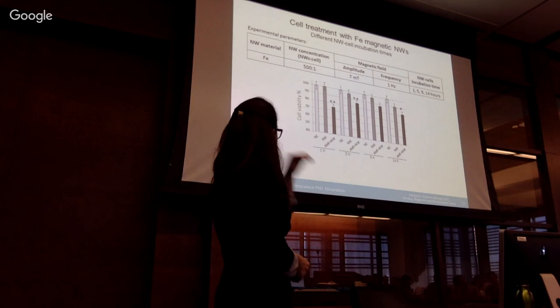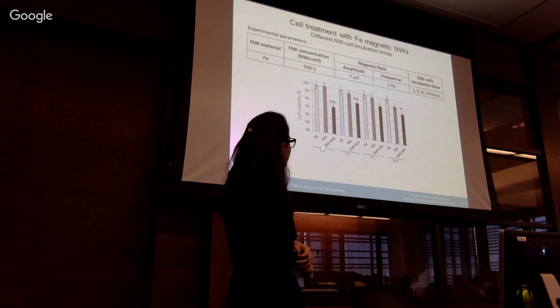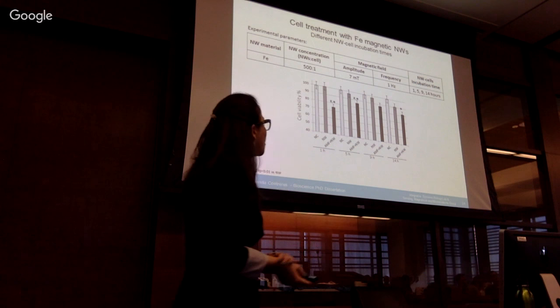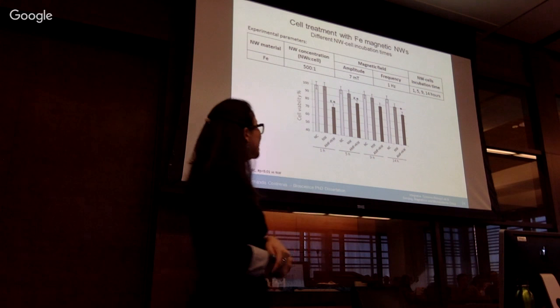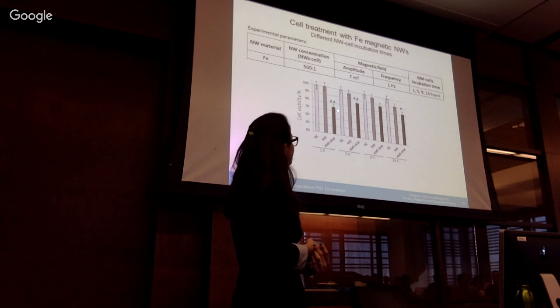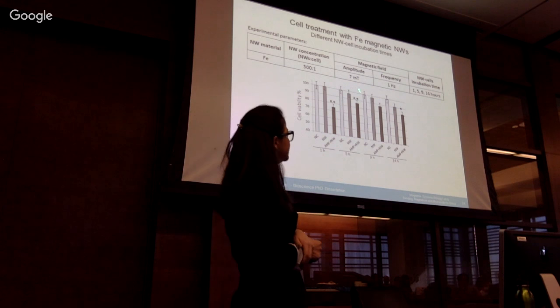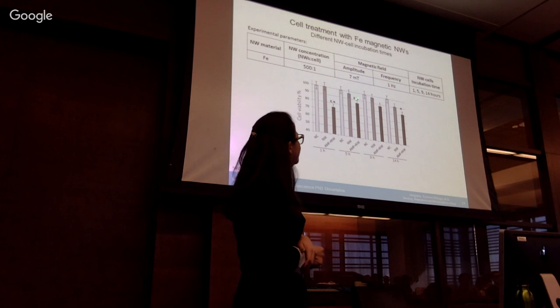So again, cell viability measures. And you have here the different controls and the application of the treatment for the different incubation times. Let's pay attention to the dark bars, which correspond to the treatment. For this field of 7 millitesla, even though I increased the field intensity, meaning that I increased the force, the viability drop was similar to the one observed for 0.5 millitesla, the field I applied before. And incubating for longer times didn't have a positive effect in reducing cell viability further.